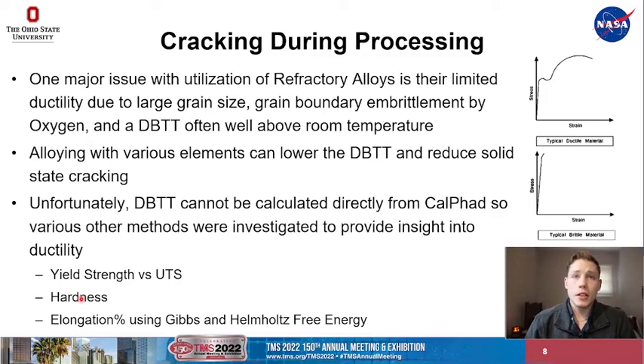So for the solid state cracking, one major issue with the use of refractory alloys is that they tend to have a limited ductility due to the large grain size, grain boundary embrittlement from oxygen, and a ductile brittle transition temperature that is well above room temperature. So if we could calculate where the ductile brittle transition temperature is and alloy it with various elements, or model alloying it with various elements to see which of those elements help reduce the ductile brittle transition temperature and reduce the solid state cracking, that would be beneficial.